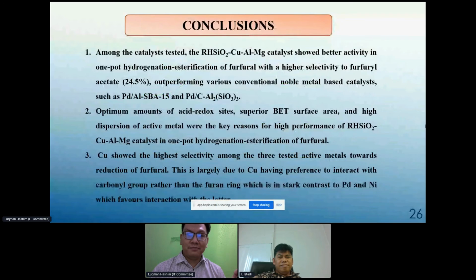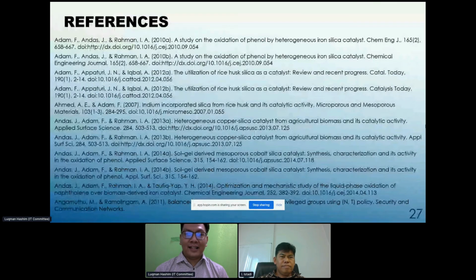Okay, for the conclusion, basically in short, copper is good. It outperforms some other conventional noble metal based catalysts, such as Pd/Al-SBA15. And this is very much due to copper's inherent selectivity towards the carbonyl carbon, which leads to formation of furfuryl alcohol. This is also helped by its good BET surface area and high dispersion. And that is all from me. I hope you enjoyed it.